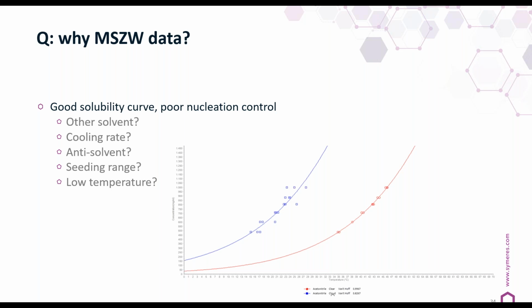So it raises certain questions in the phase where you have experiments at 1 milliliter scale already. So should you use another solvent or solvent mixture? Is your cooling rate okay, or should you lower the cooling rate and get more control on your nucleation? Maybe if a cooling crystallization doesn't give you that good a result, should you use an anti-solvent to start your nucleation? Or what is the good range to have your seeding if you want to have complete control of your process? On the other hand, when you look at a cooling process, you can also see down to what temperature you should go.